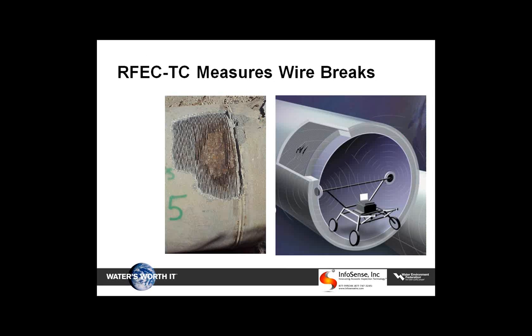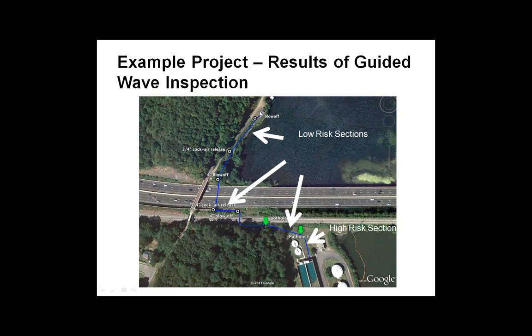The remote field eddy current measures the actual wire breaks, and it's a little bit more of an expensive technology, but we want to use it where we should be using it. What we found is that using the very inexpensive technology as a screening tool, we used the guided wave for the entire section of pipe from the intake all the way to the treatment plant, and we found that there were no major problems in the first 3 sections. But once we got inside the limits of the treatment plant, that's where we had a lot of problems.